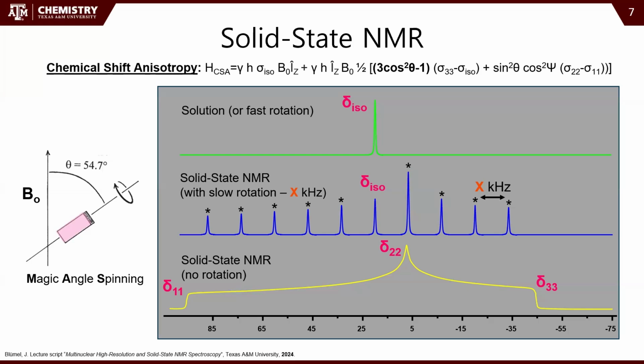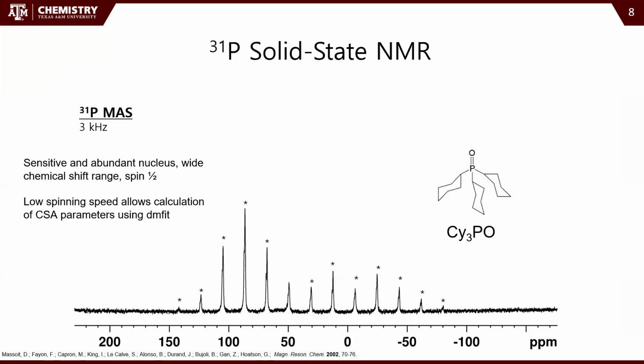And so instead of the big broad shape, we get the isotropic peak and then discrete rotational sidebands at intervals of the rotational speed. And you can see that these sidebands kind of mimic the shape of the chemical shift anisotropy. And so we can plug in the intensity of all of these rotational sidebands and back calculate the delta 1,1, 2,2, and 3,3 values to characterize the material. So that's what I did.